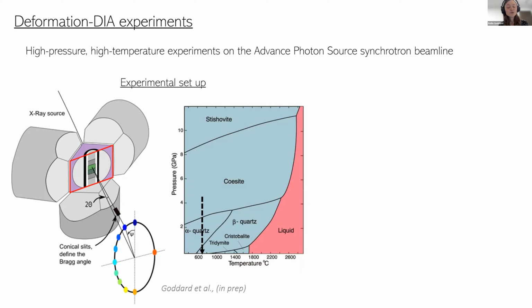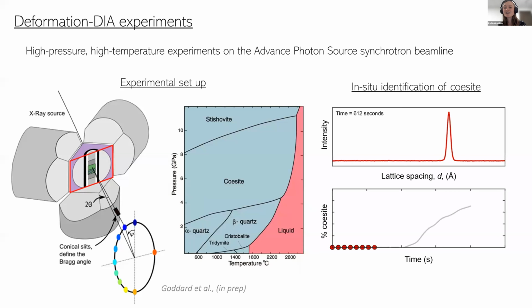Now, what's particularly cool about this setup is that it's situated on a synchrotron source, which means that we're firing X-rays at the sample, and we're able to get in situ stress measurements and also in situ strain measurements by looking at X-ray shadowgraphs. But more interestingly, for what we're interested in, to do with the transition from quartz to coesite, is that we can identify in situ when coesite forms, which you wouldn't be able to do in any other sort of rig or press that you have.